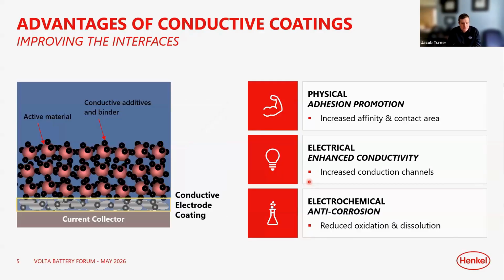So when we look at the schematic, taking that previous cartoon and looking at the cross section of this layered electrode structure, we have our active materials here, the current collector, and as I said, sitting in between is this conductive coating. Now, these coatings are typically very thin. You'll never really see them much more than 2 or 3 microns. Typically, the state of the art is pushing to 1 micron or even lower yet. So these are really thin comparatively to current collectors and especially to the active materials, where they might be tens, even hundreds of microns thick.